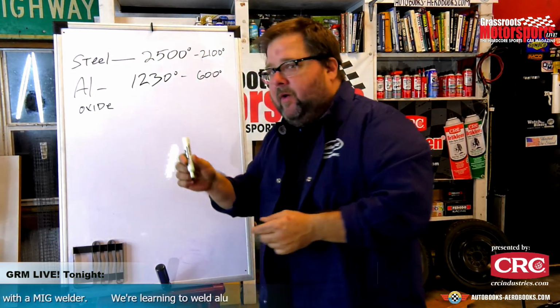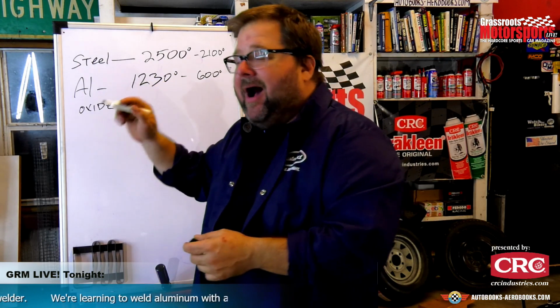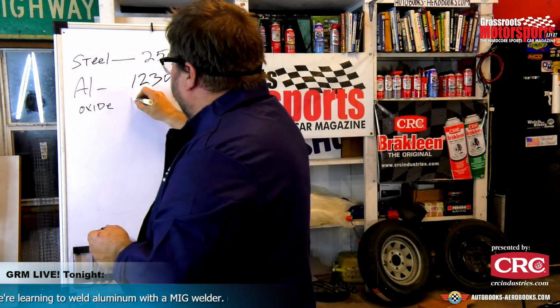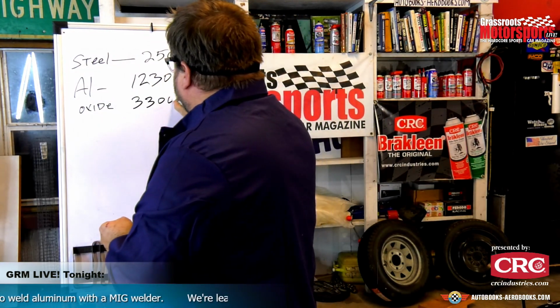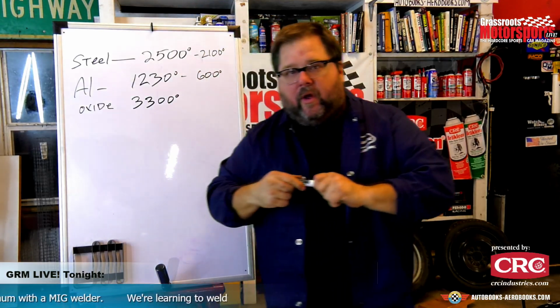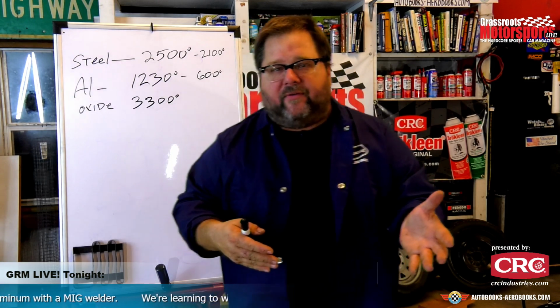Aluminum melts at 1230 degrees. Aluminum oxide is good to about 3300 degrees. So you can see that is a way higher temperature than the base metal. So if you're trying to weld through aluminum oxide, you're going to have a really, really hard time. By the time you blast through that oxide layer, you've long melted the base metal underneath that. So it's very, very important to deal with that oxide layer before you start welding aluminum.